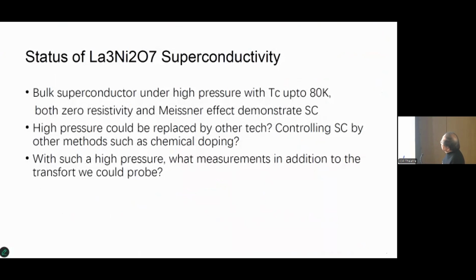So that is a brief summary of the current status of this two-layer nickelate superconductivity. Okay, its Tc is up to 80 Kelvin. So that's above liquid nitrogen temperature. Okay, and zero resistance and Meissner effect are also confirmed. And of course, the question remains whether the high pressure could be replaced by other techniques, such as chemical doping, to control superconductivity by other methods. And of course, it remains a problem because at such a high pressure, we don't have many experiments except the transport experiment. But people are thinking about possible optical measurements.